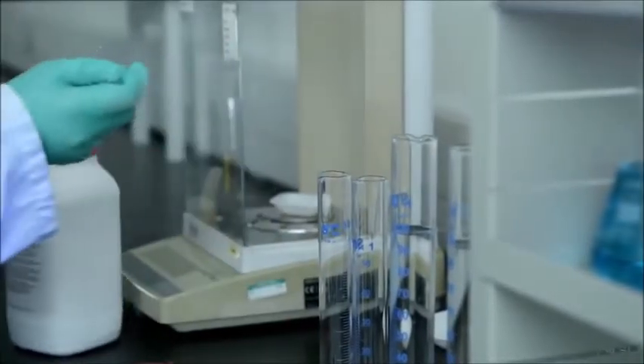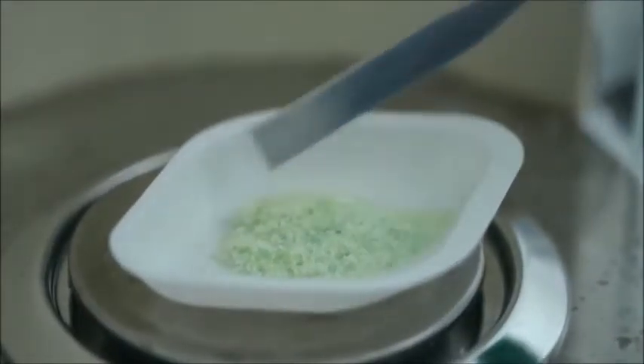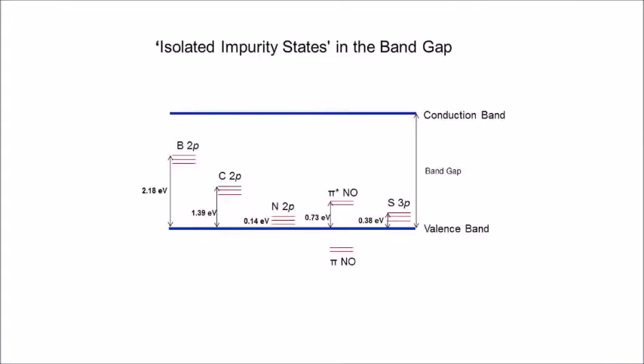Recent investigations revealed the fact that band gaps of anion-doped titanium dioxide are actually not narrowing, and the visible light absorption is resulting from the isolated impurity states located between the valence and conduction bands. For example, the isolated energy states created by boron is located 2.18 electron volt above the valence band. It's also reported that cationic sulfur doping creates an additional S3P level positioned 0.38 electron volt just above the valence band of titanium dioxide.